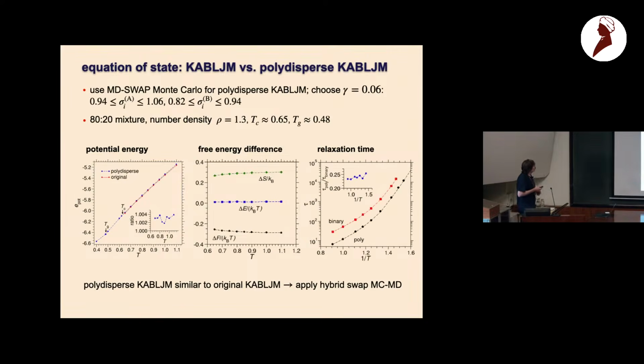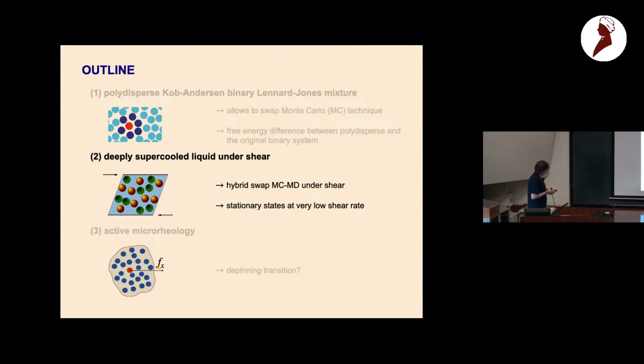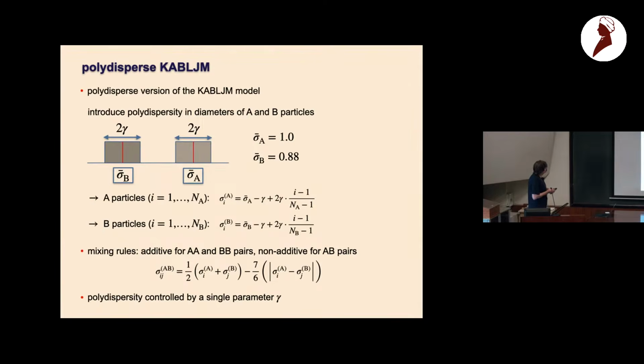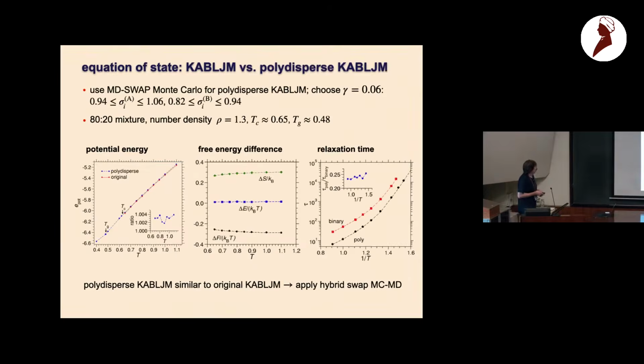So we perform the swap Monte Carlo for this polydisperse Kob-Andersen-Lennard-Jones mixture, and we choose for this a value of gamma of 0.06, which means that the width of these distributions here, of the diameter distribution, is such that they meet each other here. We have a relatively broad distribution. We work at a density of 1.3. Tc there is around 0.65, and the glass transition temperature with the swap dynamics is at 0.48.